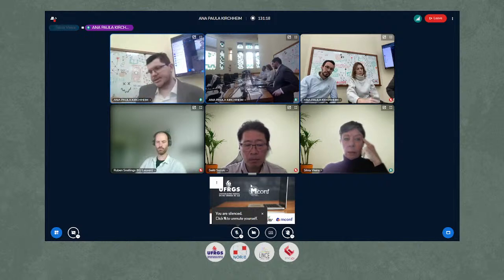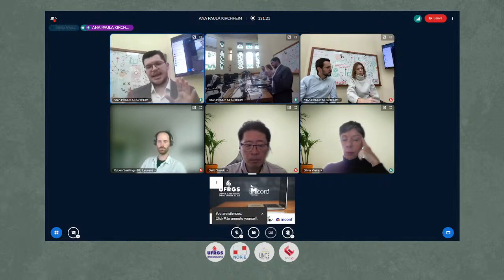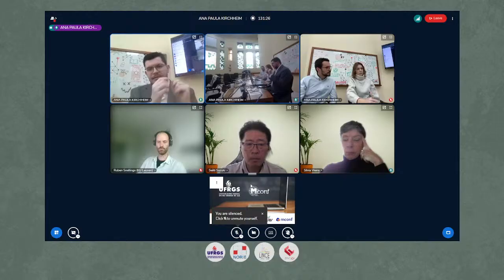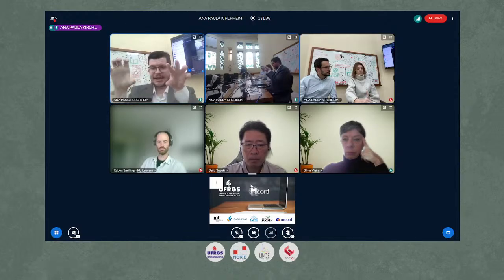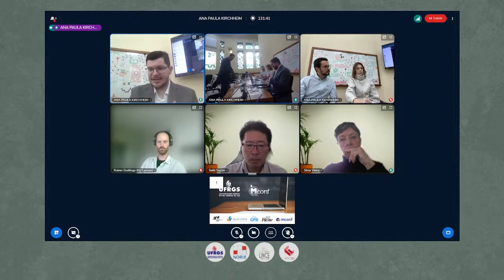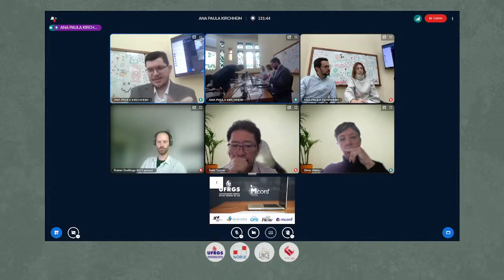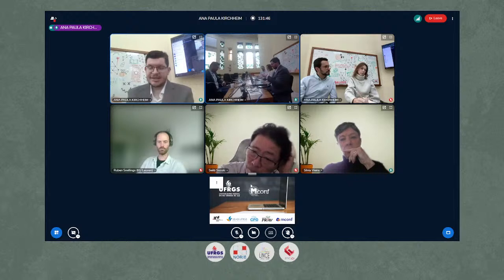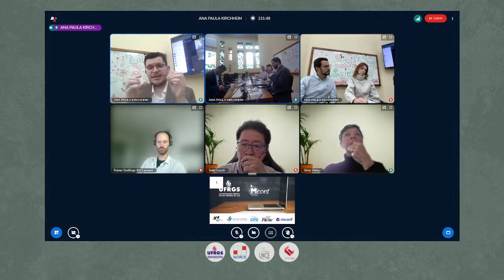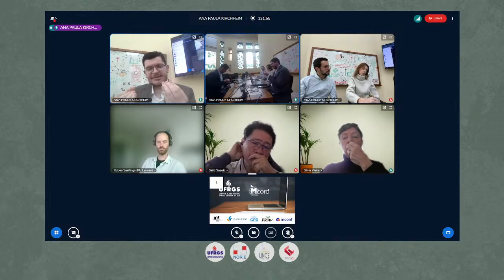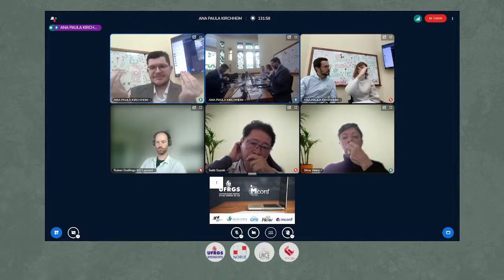Okay. Yeah, this was strange at first for me, but what it is saying is that if you have more sulfate in the clinker, we obtain a higher sulfate demand. Because in the sulfate content, I am considering the sulfate in clinker and the sulfate as gypsum. So if you have a clinker without sulfate, this will need less total sulfate than a clinker with high sulfate itself. This for me is like the sulfate in clinker is not as effective as the sulfate coming from the gypsum.